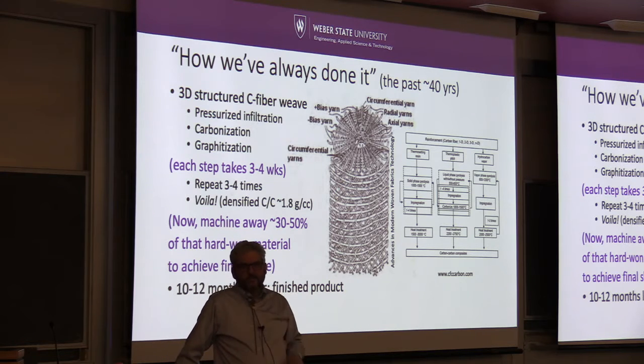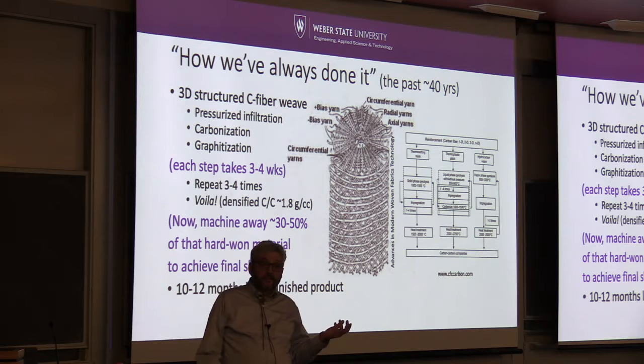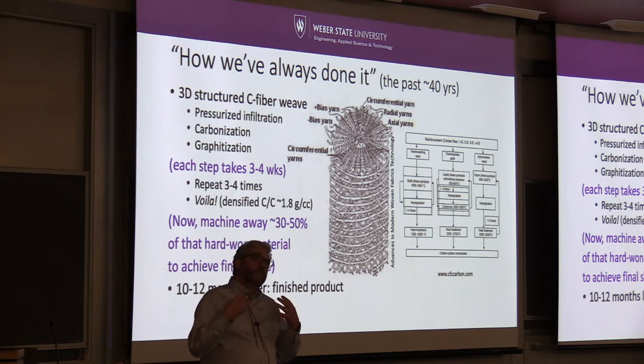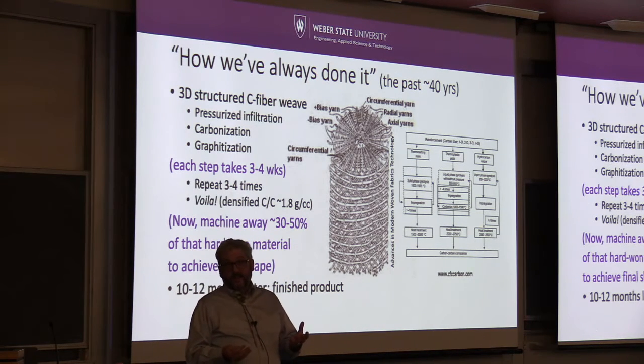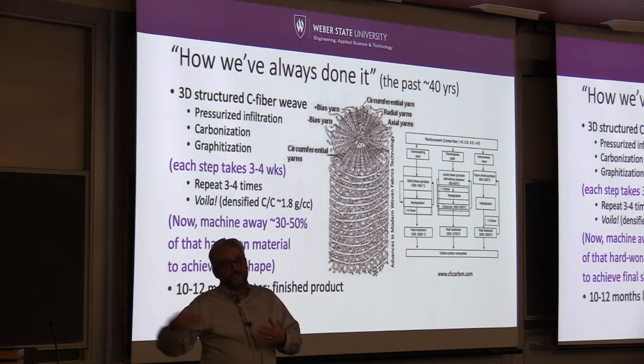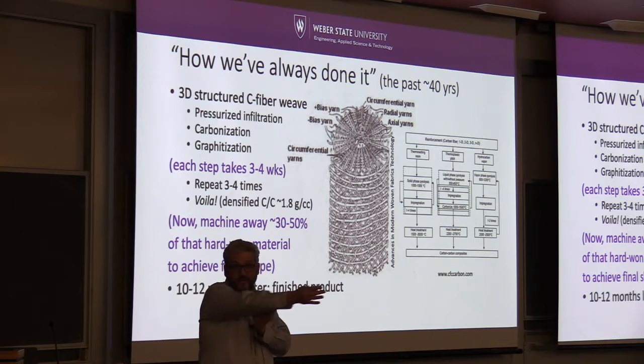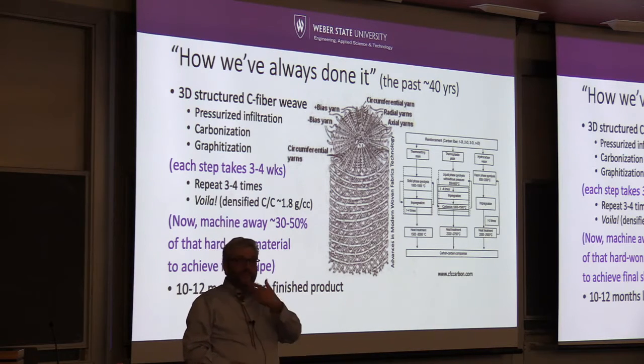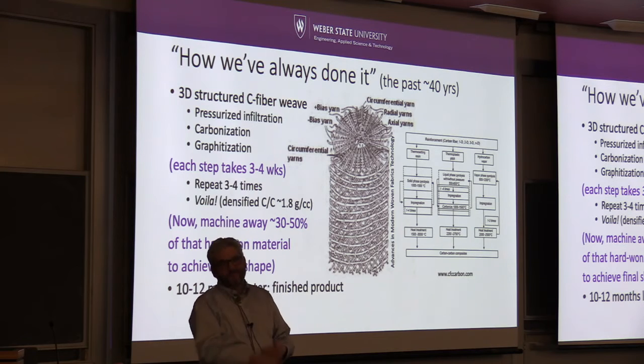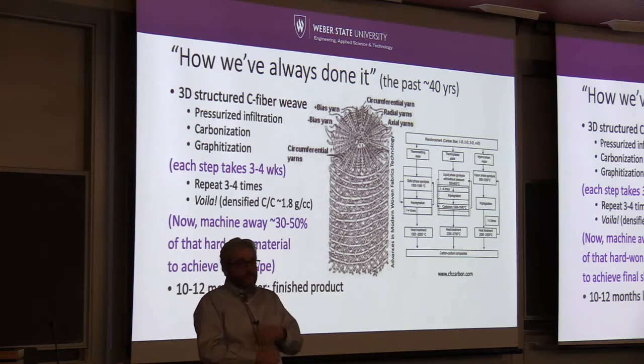Audrey, right? Yeah, can you modify the porosity at all, so that way you get more to come in? That's right. That's one of the big things that they do. They say, well, I don't want too high of a carbon density, because if it cross-links too much, then it's hard in the graphitization cycle to crack it again and create those ingress paths. So it's not necessarily porosity thereafter, it's pathways. Yeah, so that's good. That's one way. Any other ideas?